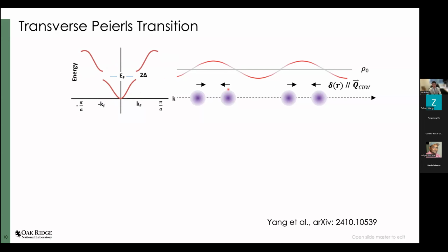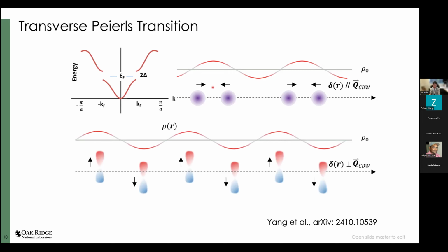So the question is, how do we create a transverse lattice distortion? Turns out it's quite simple. In real materials, we don't necessarily have isotropic s-orbital electrons. We can have conduction electrons with p orbitals. Once you have a very anisotropic orbital, you can imagine the transverse lattice distortion can affect your conducting electrons more. Then in this case, you're going to have a transverse charge density wave.